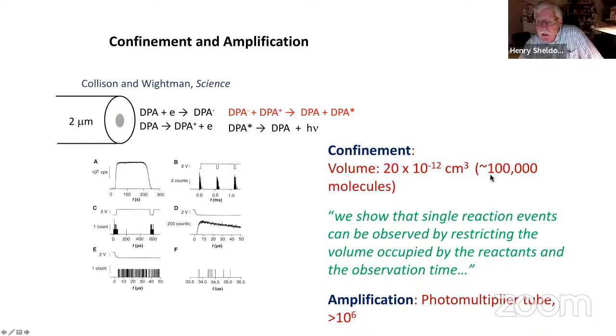All right, so the way they take the 100,000 and get down to one event is by resolving it in time. All right, so this is the ECL signal, the fluorescence signal, on a time scale of hundreds of seconds. It's a continuous signal measured at the photomultiplier tube, and then you crank up the resolution by 1 million, and you can see the little blips. And they wrote in this paper, it's the same thing that I'm telling you, that we show that single reaction events can be observed by restricting the volume occupied by the reactants and the observation time. All right. Okay, so that's the confinement part of this. And then the amplification is trivial here. It's a photomultiplier tube with a gain of greater than 1 million.